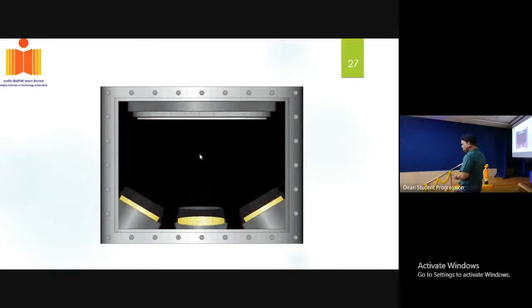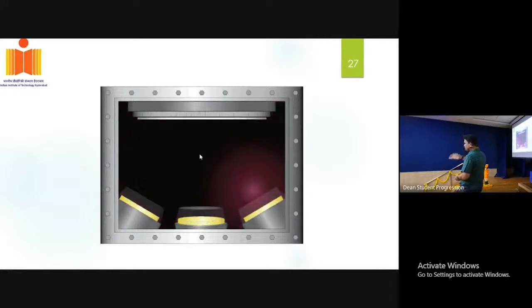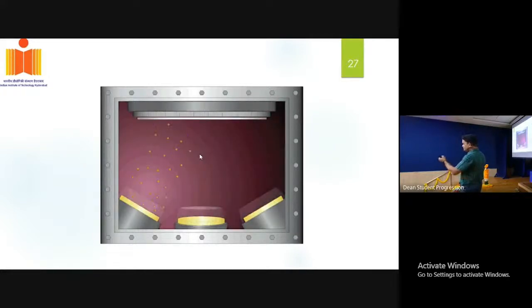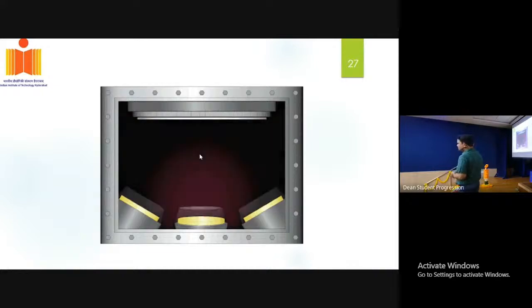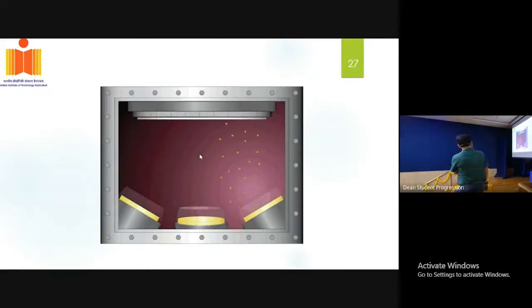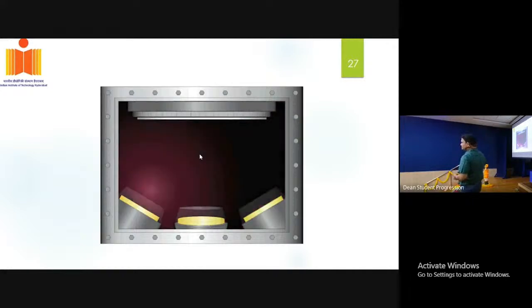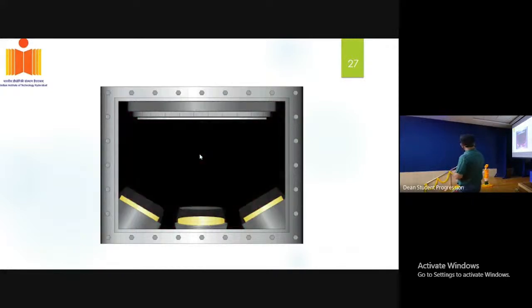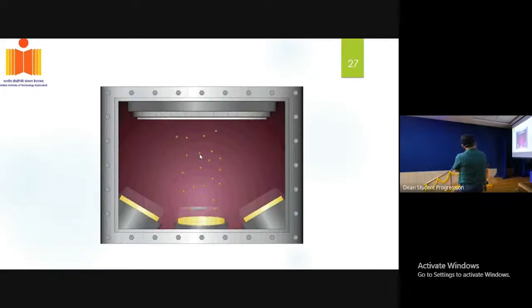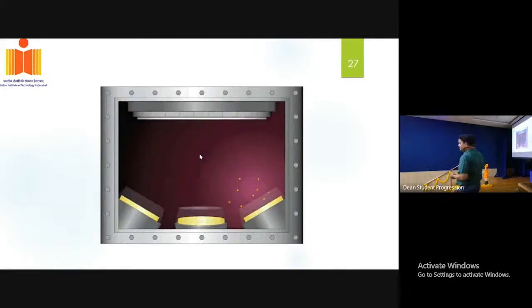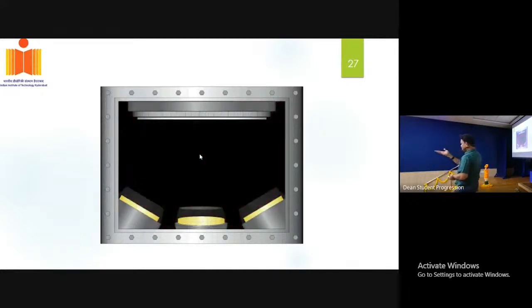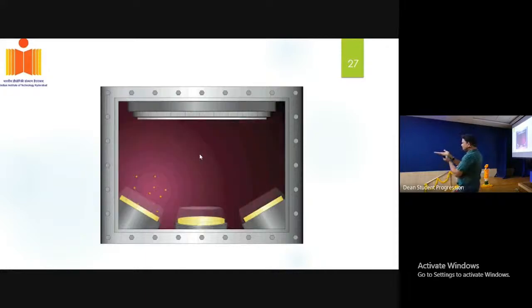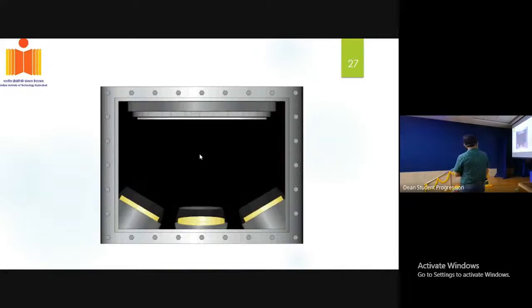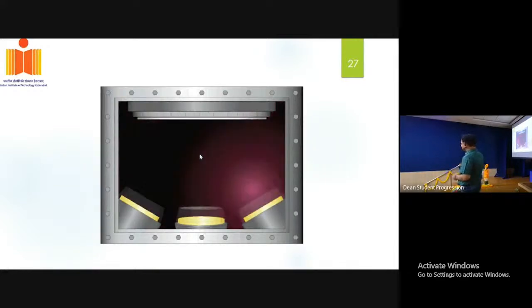What I mean by uniform thin film is that you should not have any pores in the device. Any pores means there should not be any gap in the thin film. So to avoid the gap or the defects in the sample, we do the substrate rotation, so that uniform films can be deposited. On top of that, you can also apply the substrate temperature, so that when you apply the heat, the top molecules will be very active, so that there will be good adhesion between the thin film and the substrate.